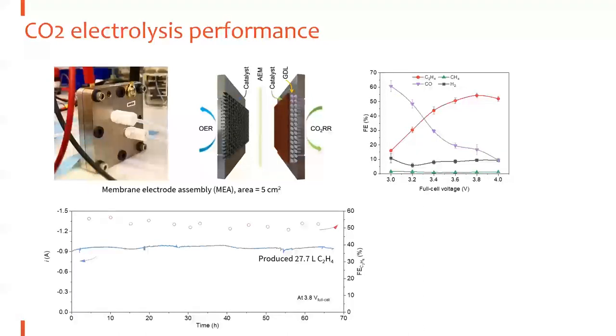Using this MEA device, we evaluate the stability of the material. And we found that within around 60 hours, the selectivity of ethylene remains stable, and we are able to generate around 28 liters of ethylene. Actually, this is quite remarkable because this is an emerging technology. But you may ask us, why do we stop here? Because everything is looking promising. The current density is stable and the selectivity is stable.